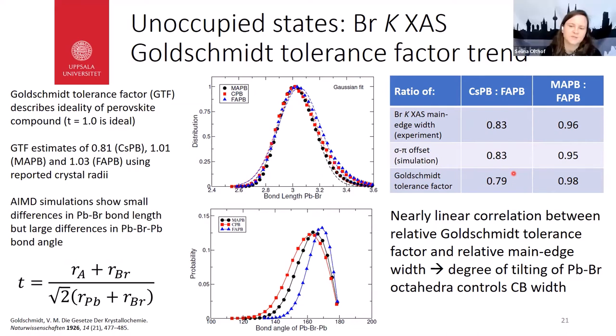Yeah. Thank you. It goes in the same topic. So very interesting about this octahedral tilting that you see this correlation. I'm just wondering if you could prove this by measuring at different temperature, so by going from orthorhombic to cubic for the cesium lead bromide. Yeah, that's definitely a good way to check as well. So it's possible in your setup to do this? At P64, it's possible to heat and cool the crystals. I think these experiments are quite accessible.